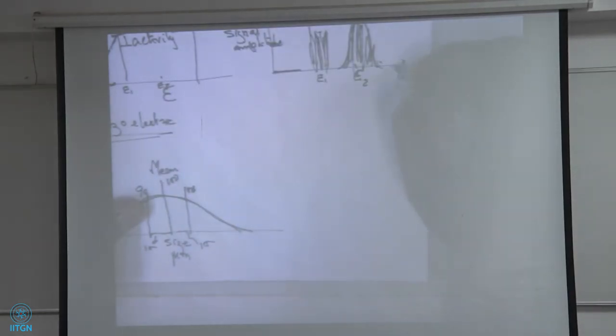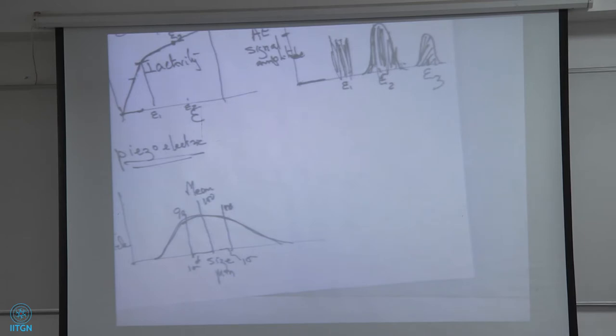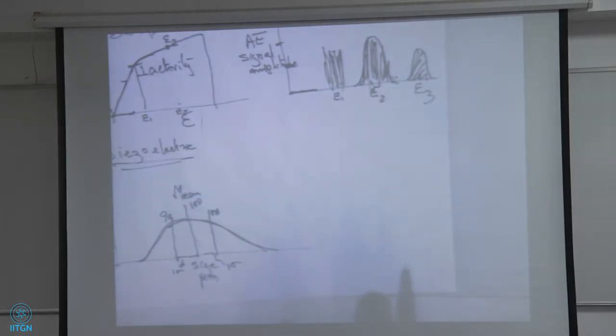And then, as you keep going, the small particles will start to crack. They need higher stress, epsilon 3. And you get another peak. Ta-da. That's a very good one-to-one relationship you see in this material. I have the data if you want. I can show you from the paper from a long time ago.